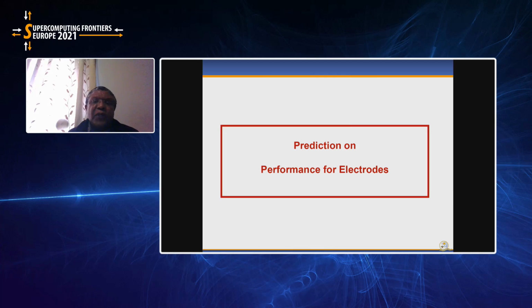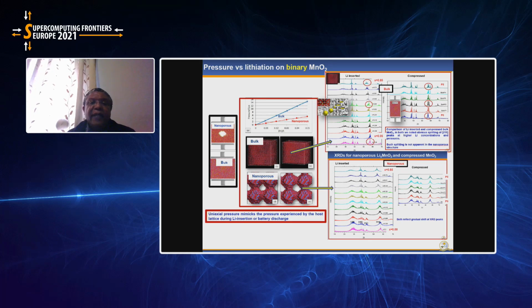Now, I'm going to look at another way in which we examine the performance of these materials, how we predict the performance. In this case, we can apply uniaxial pressure to what we call the porous structure and the bulk structure. When you apply the same strain to the porous and the bulk structure, the bulk structure experiences a very high pressure.